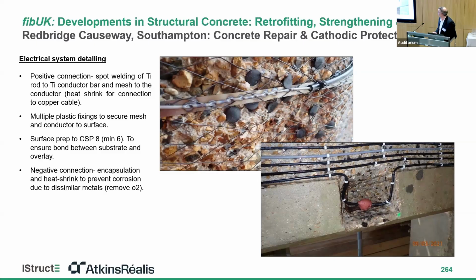In the top picture, you can also see how aggressive the surface prep is. Using an overlay system, grit blast isn't sufficient. Early systems tended to debond. With this, we use what's called a roto mill, and that gives you a very aggressive finish, which has proven so far to give a very good bond for the overlay.